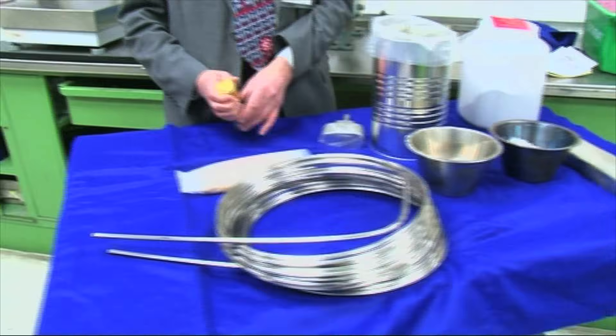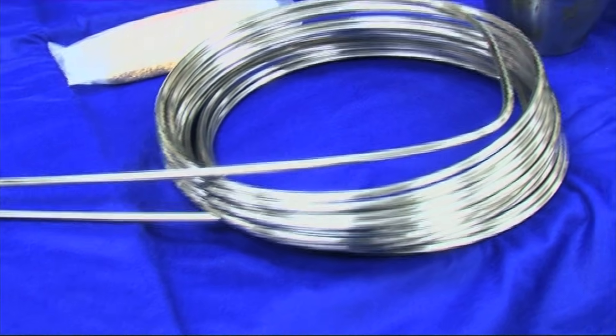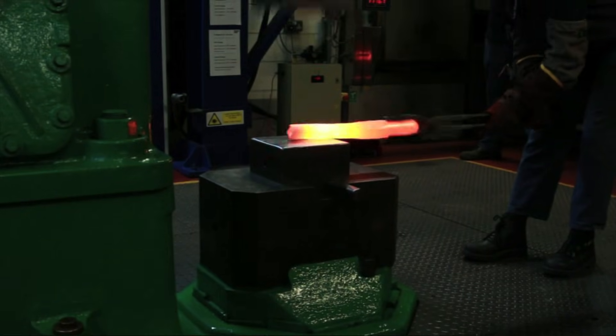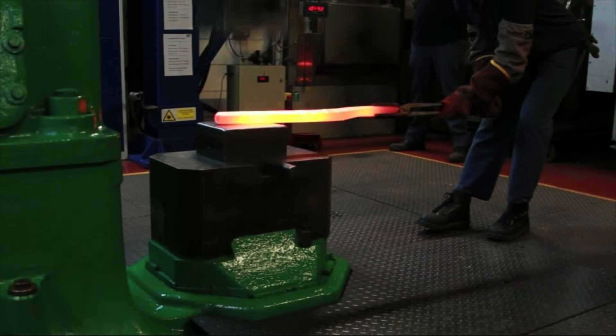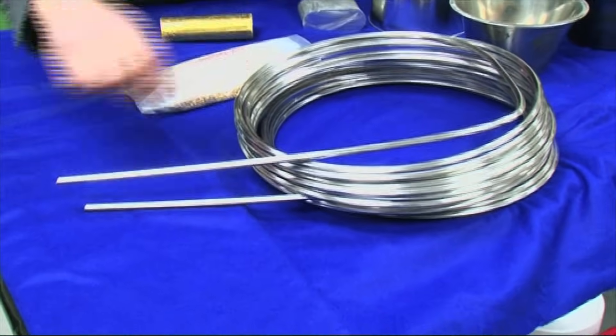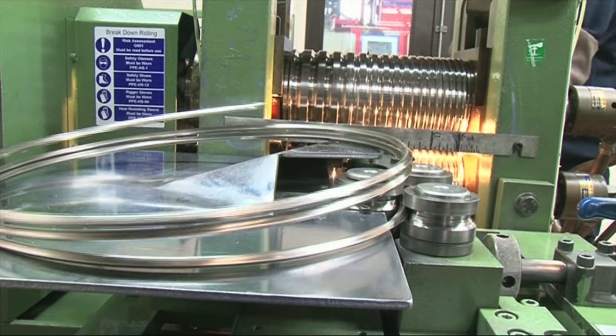The difference between this and gold is that you can use platinum as a catalyst for all sorts of chemical processes. So ingots like this are then turned into bars by hammering the ingot very hard with a heavy hammer when it's really hot. The fantastic thing is, as it hammers it, the metal gets hotter — the energy of the hammer is turned into heat, and it starts glowing redder and redder. Then they take the hammered bar and draw it down through a series of dies, so it first gets into a coil like this. As the coil comes out of the die, it coils itself up — it's almost like magic. You see this coming up and going round and round and round. I was mesmerized.